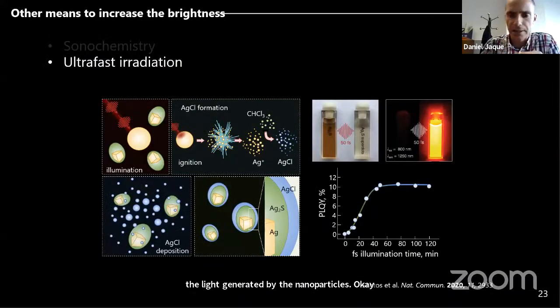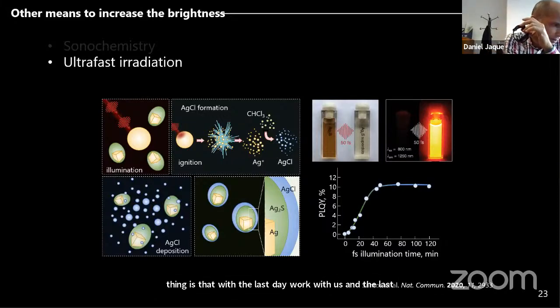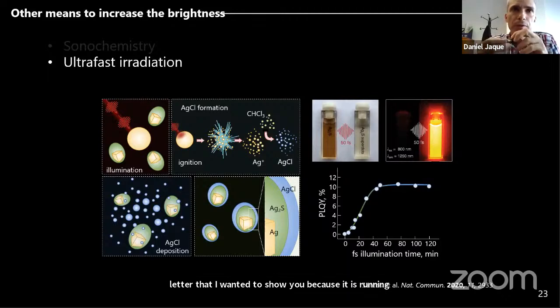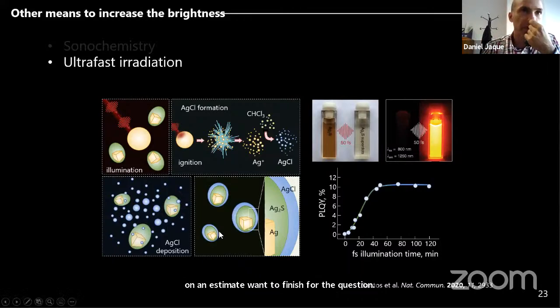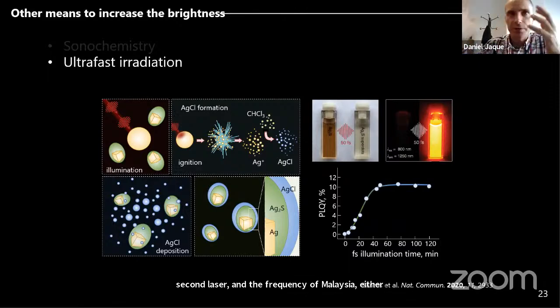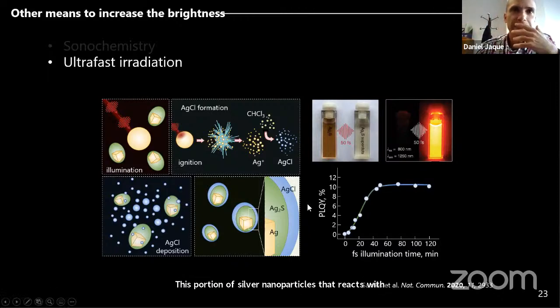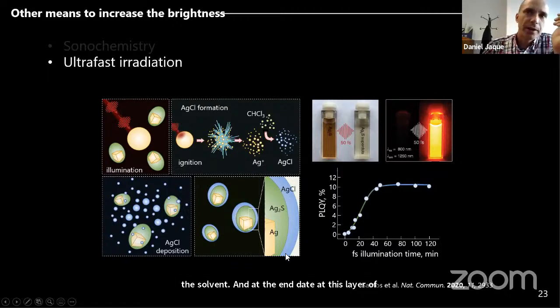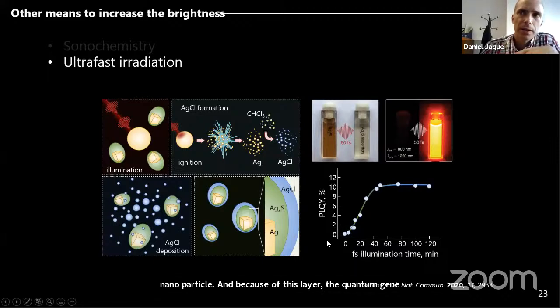Let me finish with the last work, which is the last method that I wanted to show you, because the time is running and then I want to finish for the questions. We can improve the nanoparticles by what we call ultra-fast irradiation. It means that you have the nanoparticles, you use a femtosecond laser, and the femtosecond laser triggers the explosion of silver nanoparticles that reacts with the solvent and at the end creates a protective layer of silver chloride around the nanoparticle. And because of this protective layer, the quantum yield of the nanoparticles increases a lot.